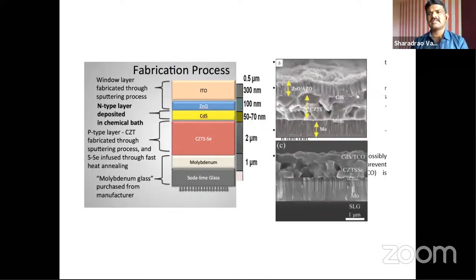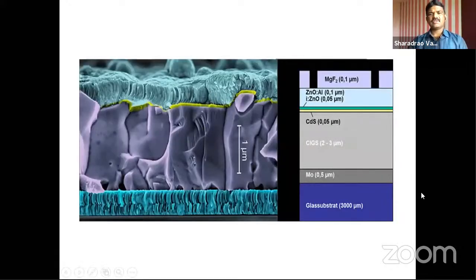This is an SEM image of a CZTS and CZTSe type of solar cell. You can clearly see the molybdenum or moly layer over which CZTS grains were developed or deposited, on which a very small layer of CdS was deposited, and where you can see the back-end processes, the TCO and ITO, deposited over it. So I will show another figure. Here you can see clearly how the solar cell looks. It contains the moly layer, over which good quality grains were deposited, having a size of about 1 micrometer. And on it, the yellow colored layer you can see is the n-type semiconductor, which is nothing but the CdS, and over which zinc oxide or aluminum doped zinc oxide was deposited. And this is the simple structure of a solar cell, how the solar cell looks.